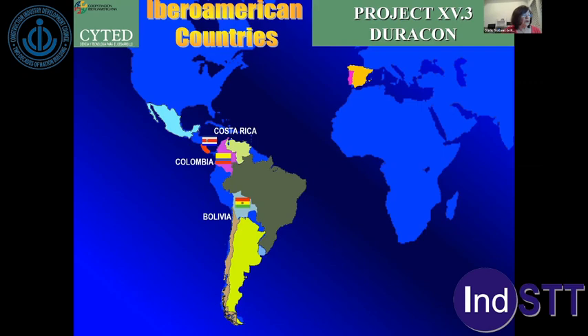Evaluation of the climatic and environmental parameters in each of the exposure sites during the test period was based on the methodology established by ISO standard 9223 for classifying atmospheric aggressiveness. This standard classifies the atmosphere according to time of wetness and the deposition rate of atmospheric pollutants, sulfur compounds, P, and salinity, S. The figure attempts to show the expected relative aggressiveness at the different test sites analyzed.